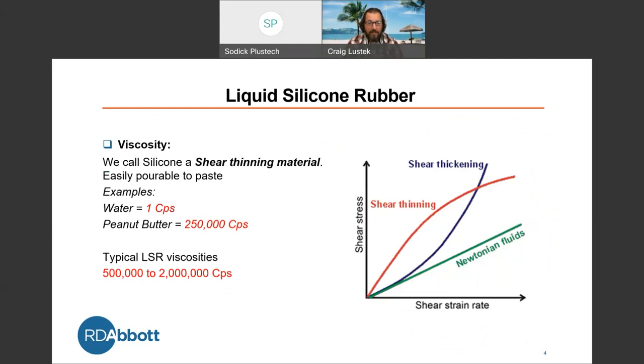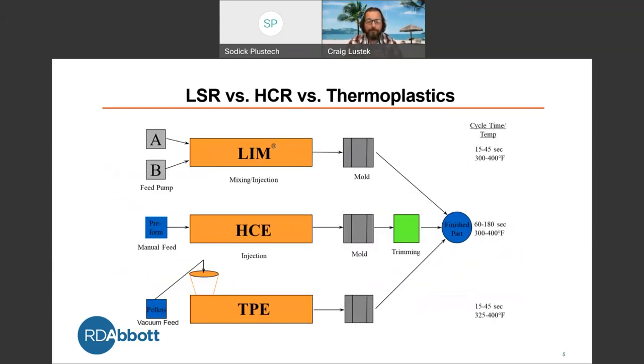Again, the viscosity, we like to call silicone a shear thinning material, and it's easily pourable to paste. Some examples, water, to give you a good example, you have one centipoise, where you look at peanut butter up to 250,000 centipoise. That's creamy peanut butter, not chunky peanut butter. Typical LSR viscosities, you're looking anywhere from 500,000 upwards of 2 million centipoise. So there is a wide range there where you can have the different types of materials, different shore hardnesses, durometers of the silicone that you're running.